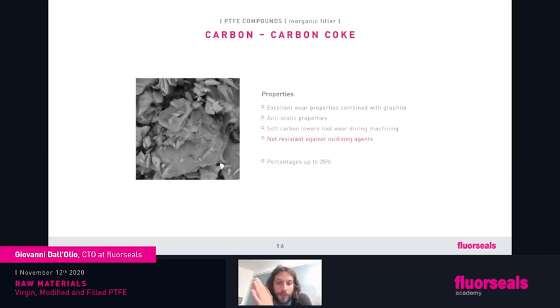It's great for flammable environments where the anti-static properties are needed, because you don't want a spark that can initiate a fire. The anti-static properties of carbon, because of its electrical conductivity, are widely used mainly in ATEX environments. But we were mentioning the difference between carbon and soft carbon. The hard carbon, as I mentioned, is a stiffer material.